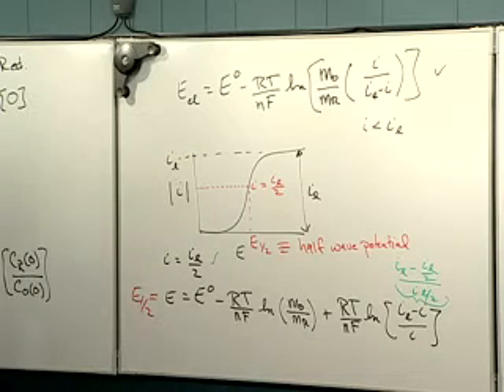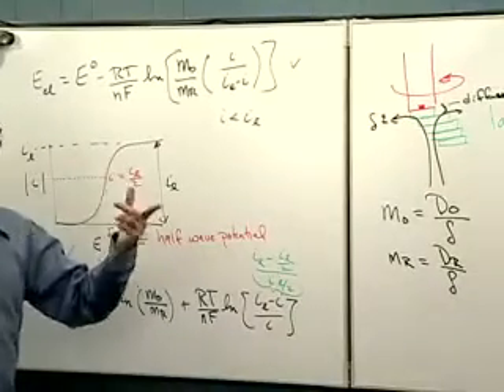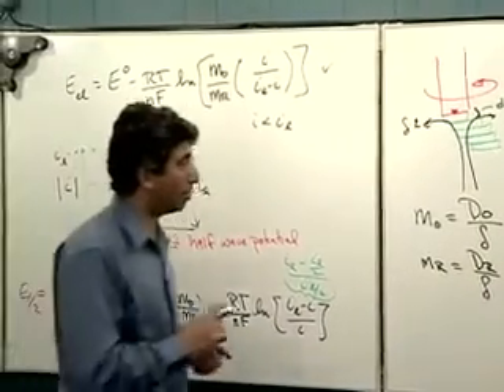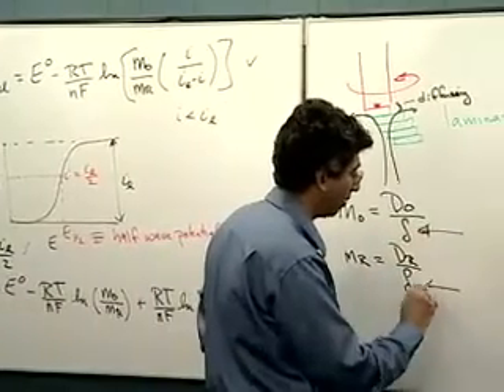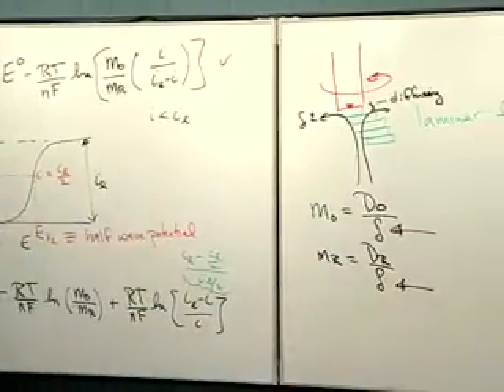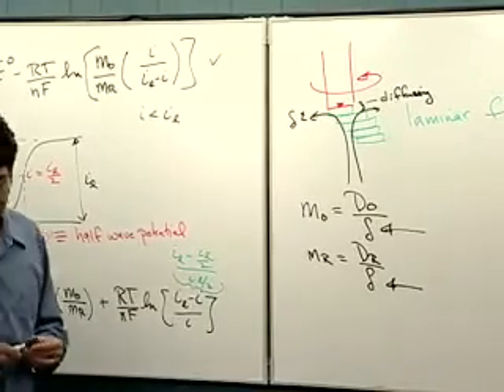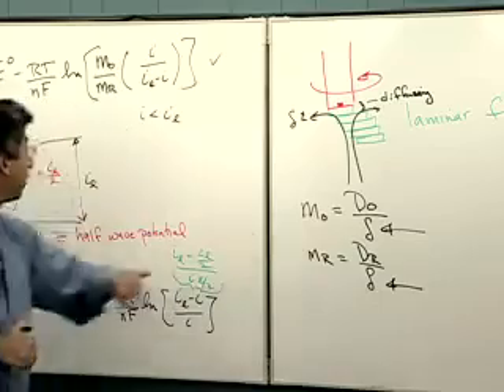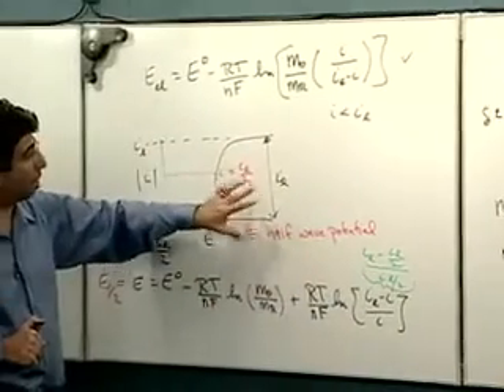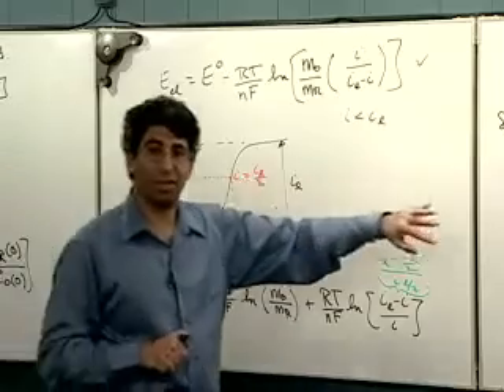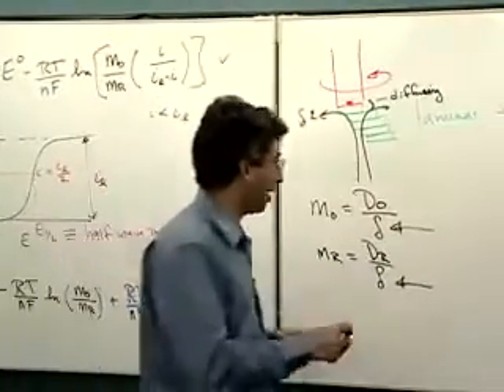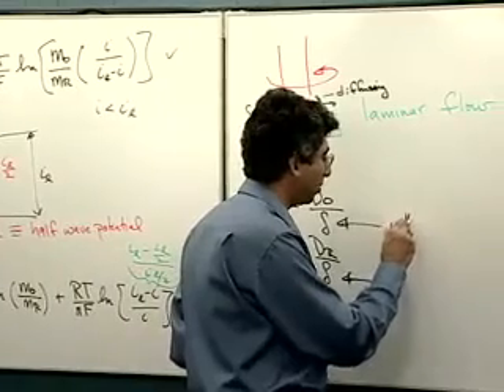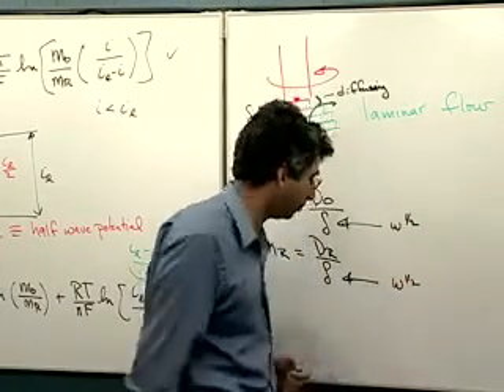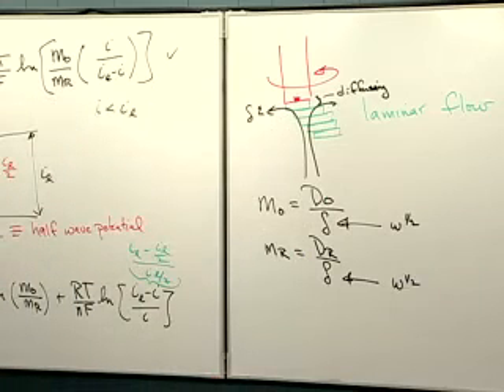Now, the one flexibility that you have here is that I can obviously rotate that electrode at different rates. And what is that doing? That is affecting the thickness of that final layer. So I can adjust delta by rotating at different rates up till this turbulent boundary. By doing that, I'm adjusting the limiting current. So plots of the limiting current versus the rotation rate, approximately, it turns out that this boundary happens to go as the square root of rotation rate, will tell me what the diffusion coefficient is for the system. That was my point number 3 on this board.